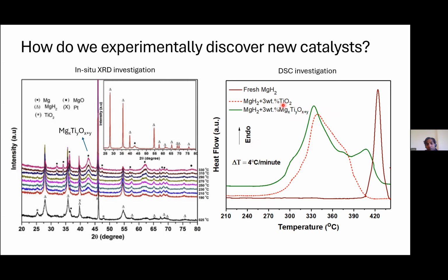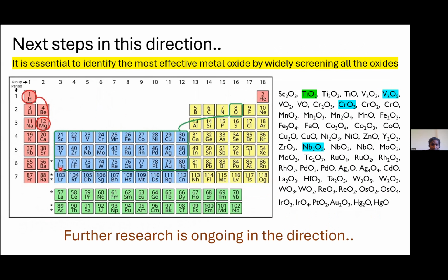I tell you pictorially, here is a periodic table. You have at least 30 transition metals. From that you can have this many oxides. It's in my collection, from whatever I know, but there can be some oxides I missed out. And also there can be ternary oxides. By mixing two different oxides, so many oxides can be formed. And from that, you can identify what can be the best active species.